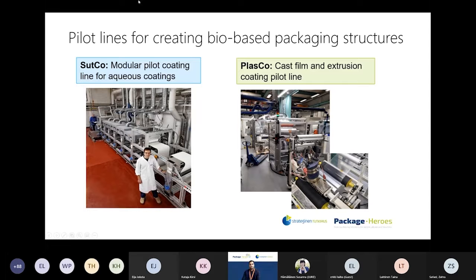And on this line, we were performing all our dispersion or cast coatings. And then we have a Plasco line, which is in Tampere. In this line, we were using cast film or extrusion coating processes. And here you can see a picture of the line. This was used basically for bio-PBSA film extrusion and coating work.